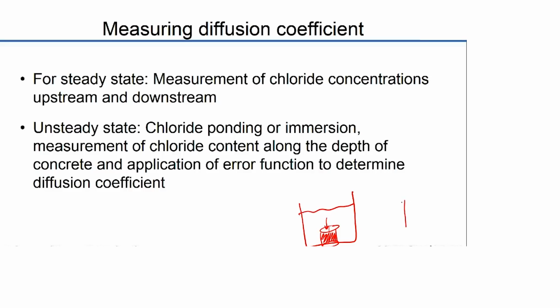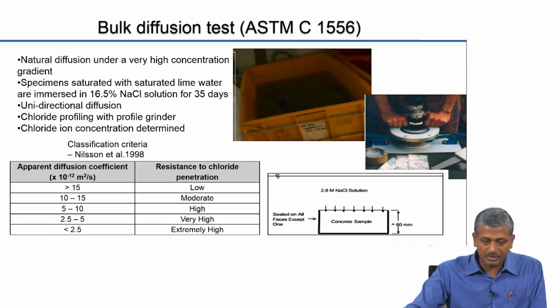And from time to time, all you have to do is section off the concrete with respect to depth and powder it and measure the extent of chloride, which is varying as a function of the depth of the concrete, okay. So that's what you do. You basically do chloride ponding and measurement of chloride content along the depth of the concrete, which can then be fitted using the error function to determine the diffusion coefficient. Again, this is what is depicted here.